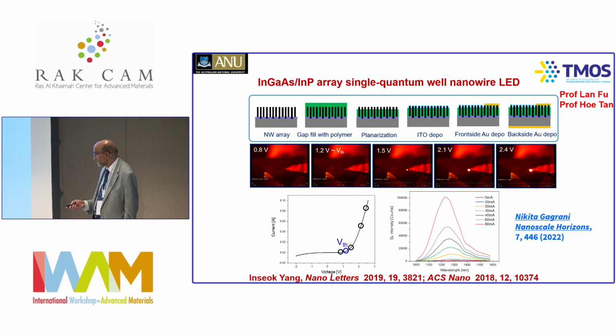Before leaving, Inseok has also made these multi-nanowire LEDs. You grow these nanowires, and the challenge is how to make contacts at the top. You can make the bottom contact here, but how to make the top contacts? We fill this with a polymer, and you selectively etch the polymer. You deposit some indium tin oxide, another transparent conducting oxide, put some metal on the side, and then put another metal here, and then inject current and look at the light emission. Again, the IV characteristics show diode-like behavior, and the more current is injected, the more light comes out. In fact, under this probe, you can see the bright light coming out.